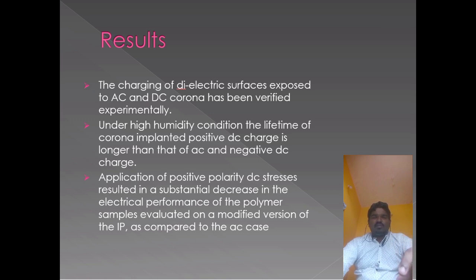In this paper, the electrical performance of several polymeric systems has been presented. Charging of dielectric surfaces exposed to AC and DC corona has been verified experimentally, and it was observed that even under high humidity conditions, the lifetime of corona implanted positive DC charge is longer than that of AC and negative DC charge. Application of positive polarity DC stresses resulted in a substantial decrease in the electrical performance of the polymer samples evaluated on a modified version of the IP, IP meaning inclined plane, as compared to the AC case.